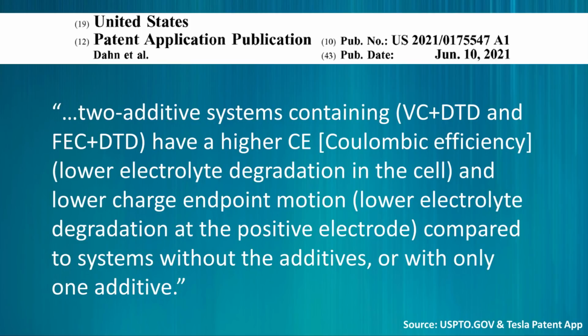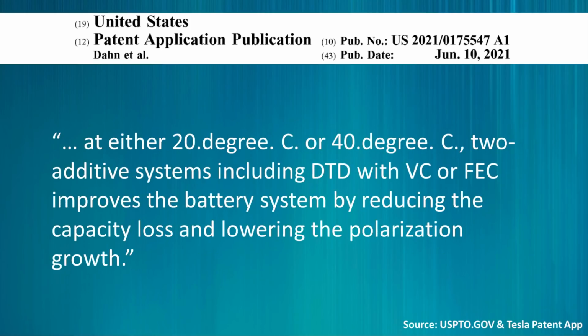First of all, they mention how these additives lead to lower electrolyte degradation. They mention two additive systems containing vinylene carbonate and ethylene sulfate and fluoroethylene carbonate plus ethylene sulfate have a higher Coulombic efficiency, which they explain as having lower electrolyte degradation in the cell, and lower charge endpoint motion, which they also describe as lower electrolyte degradation at the positive electrode, compared to systems without the additives or with only one additive. They also tested the long-term cycling of the cells and found that at either 20 degrees Celsius or 40 degrees Celsius, two additive systems, including ethylene sulfate with vinylene carbonate or fluoroethylene carbonate, improves the battery system by reducing the capacity loss and lowering the polarization growth.